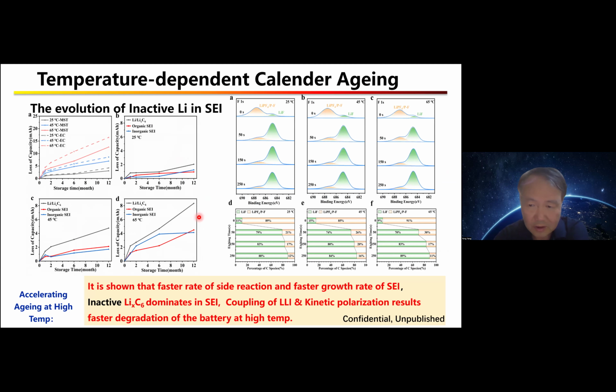And we also checked the time evolution of the SEI during the calendar aging. That is a similar conclusion as before - the faster reaction causes the faster rate of reaction and the faster growth rate of the SEI. So that is similar.